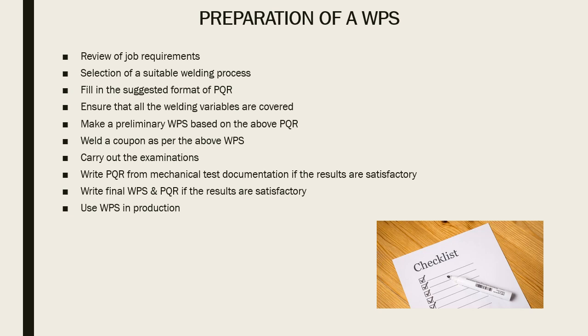Then fill in the suggested format of the PQR — rough draft your PQR. Fill in the metals, filler metals, shielding gases, and all the essential variables. Double-check it against your code and customer requirements, ensuring all welding variables are covered. Then make a preliminary WPS, a PWPS. A lot of times clients or third-party inspectors want to see a preliminary WPS before you even start qualification — to see if you have a clue as to what you're doing. That's what you'll work off of when you're out in the shop with your welder doing the qualification of the test coupon.